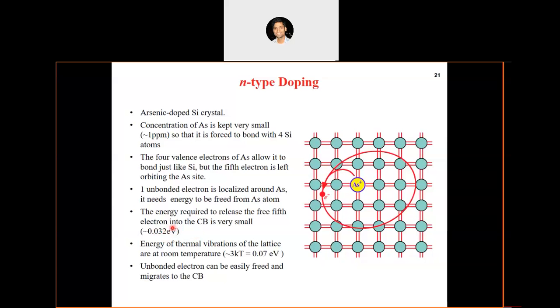Why am I saying this energy is very small? Actually because the energy of the thermal vibrations of the atoms, or the energy of the lattice vibrations at room temperature, is approximately of the order of 0.07 electron volt. So that means the thermal vibration energy itself is sufficient to free this electron. We don't need to provide any extra energy. Like for example, in the case of an intrinsic semiconductor, to excite an electron from the valence band to the conduction band, we need a very high amount of energy. We need some sort of energy source like photogeneration, or basically photons. In this case, the thermal vibrations happening at room temperature are sufficient to make this electron free, which means this electron which has now become free will go to the conduction band of the semiconductor, right?